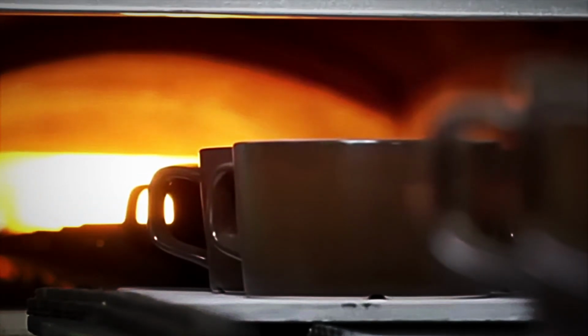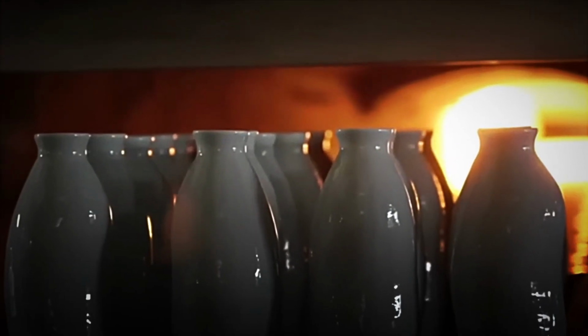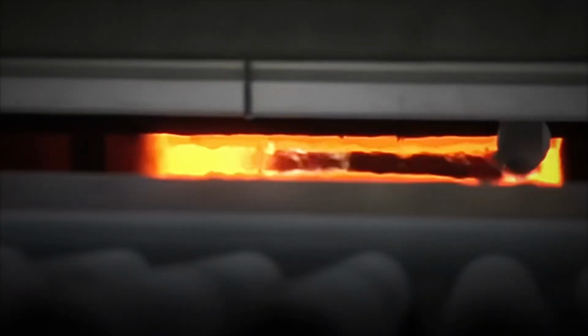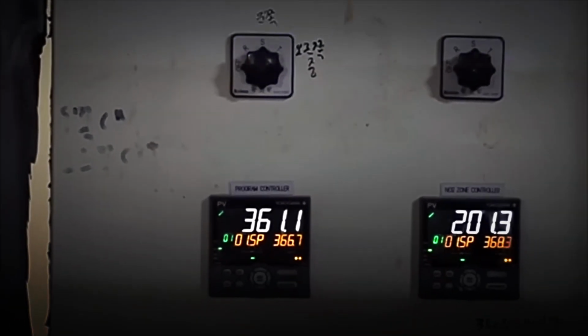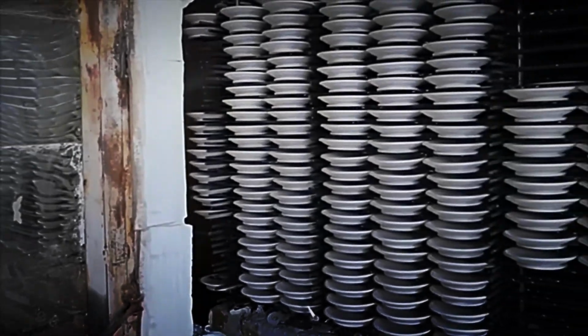In the final firing, the piece reaches its final shape. The glaze melts and integrates with the ceramic body, creating a glazed, hard, and completely waterproof surface. Temperatures can reach 2,200 to 2,500 degrees Fahrenheit, depending on the type of ceramic. Industrial kilns, again tunnel type, have arched roofs that promote heat circulation and minimize deformation.